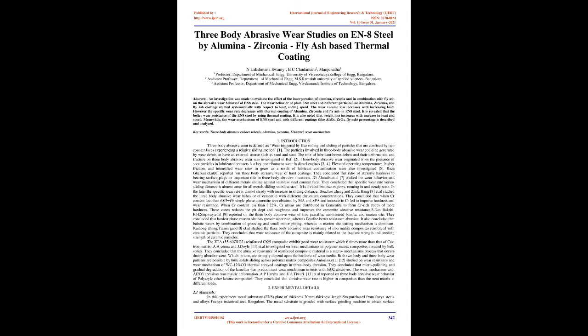It is also noted that weight loss increases with increase in load and speed. Meanwhile, the wear mechanisms of EN-8 steel and with different coatings, like Al2O3, ZrO2, and fly ash percentage, are described and analyzed. Keywords: 3-body abrasive rubber wheels, alumina, zirconia, EN-8 steel, wear mechanism.